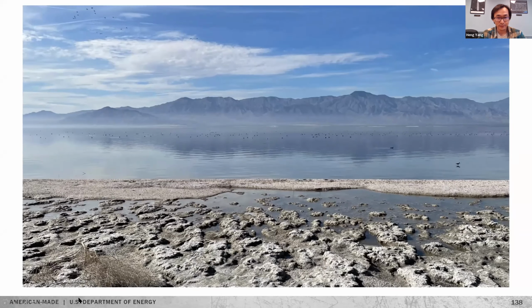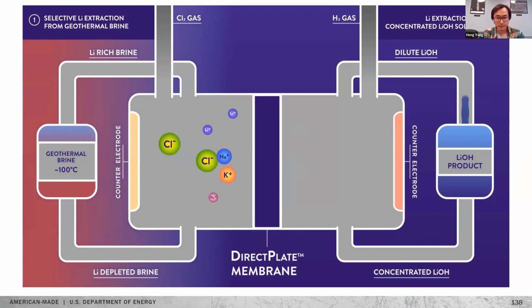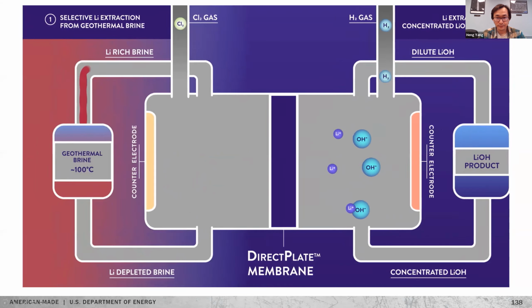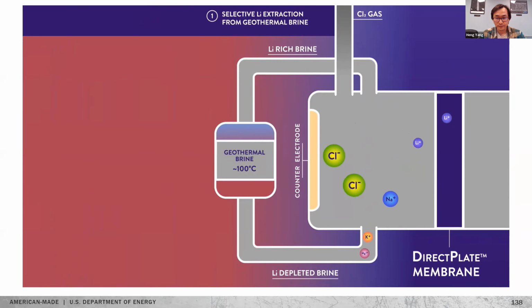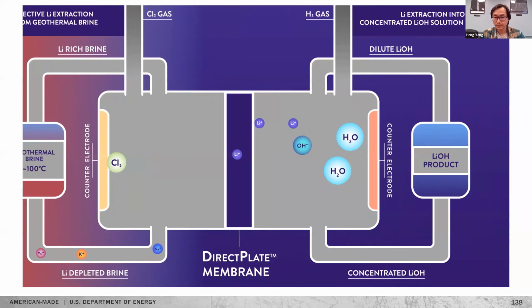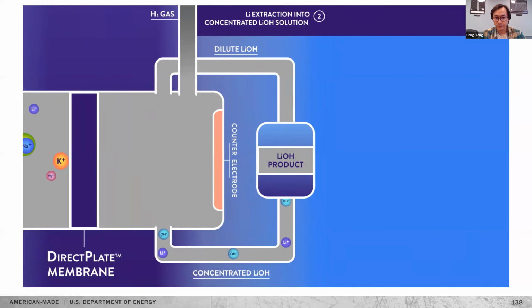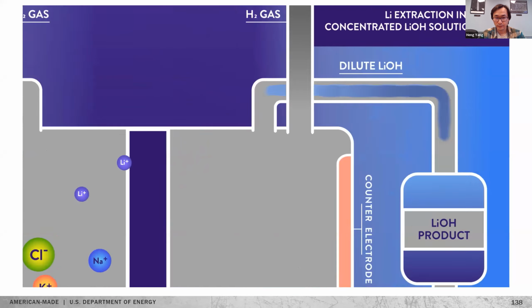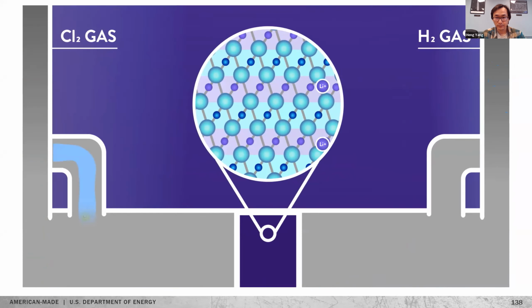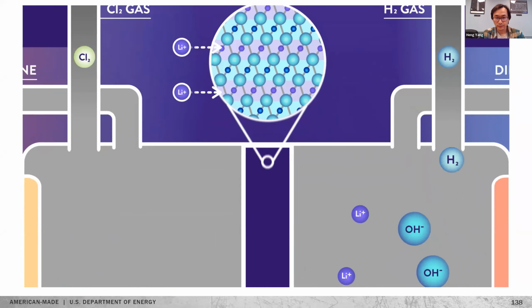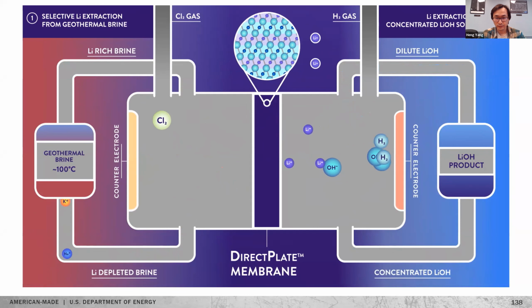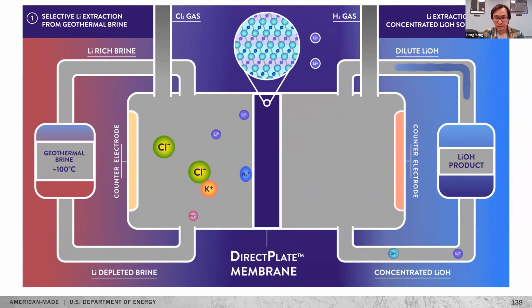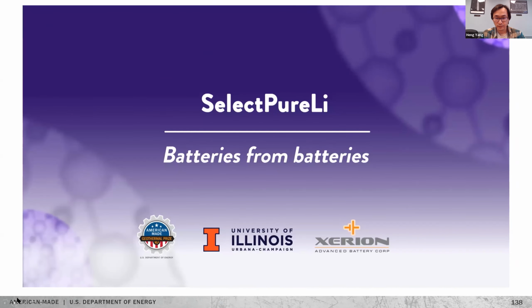The Select Pure Li team proposes a simple and energy-efficient method to extract lithium from geothermal brine and convert it into high-value lithium hydroxide. The two-stage reaction begins with the lithium extraction and intercalation into the direct plate membrane, while at the same time, chlorine gas is evolved on the counter electrode. In the opposite chamber, lithium ion is released from the membrane and combines with hydroxide ions formed from hydrogen evolution reaction, producing high-concentration lithium hydroxide solution. The key component is the direct plate membrane, an electroplated battery material only permeable by lithium ions. The estimated lithium pass-through at the Salton Sea geothermal region exceeds 24,000 metric tons per year. If fully developed, lithium extraction from geothermal brine could provide a secure, long-lasting lithium source for the United States.